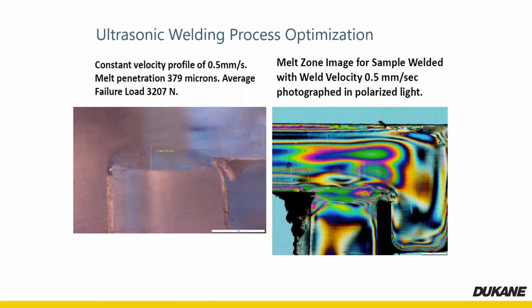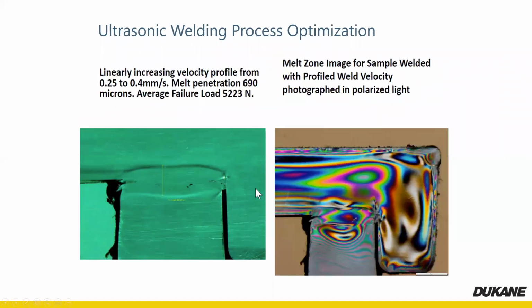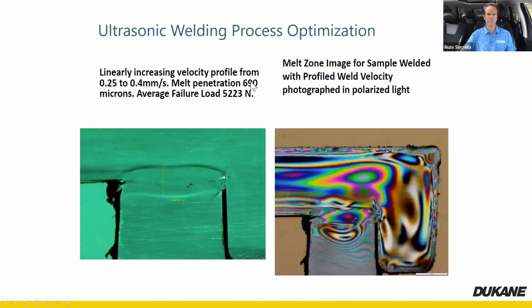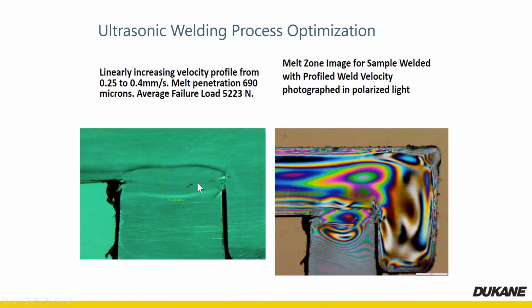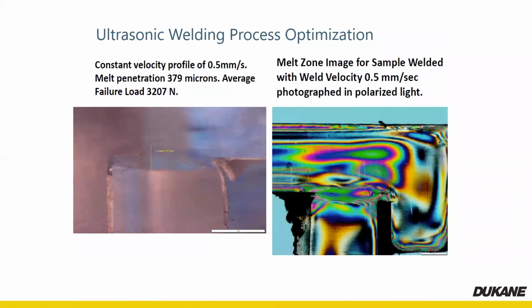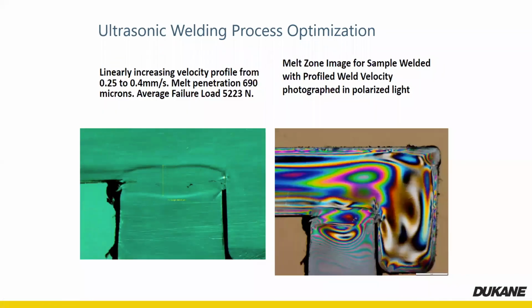So now this last slide shows some weld processing optimization. So we've linearly increased the velocity profile from 0.25 millimeters to 0.4 millimeters per second. The melt penetration now has gone from, the last one was 379 microns, we've almost doubled that at 690 microns. So you can see we've gotten much deeper into the plastic. And now our failure is 5,200 Newtons. And that is double what it was at the beginning, 2,400 Newtons, and we go up to 5,200 Newtons here. So significant pull force improvements can be made using this process.